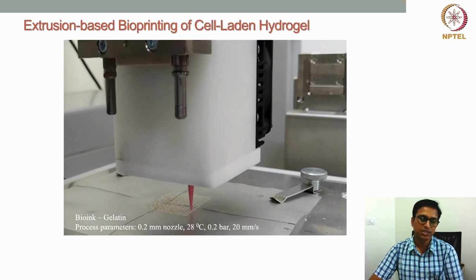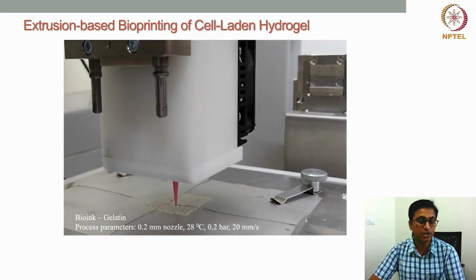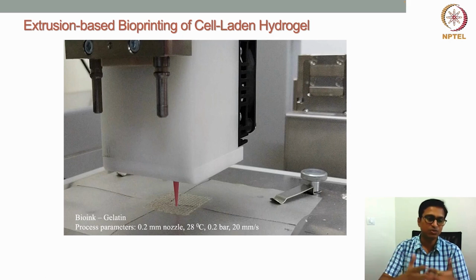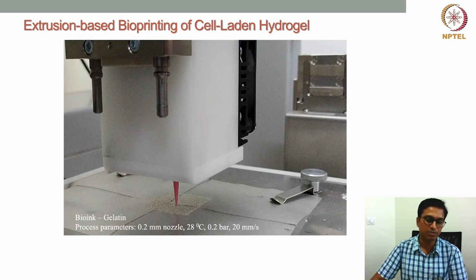But this, as I already mentioned, here the structural fidelity, the printing fidelity cannot be very good because of the nature of the hydrogel, that when you print them, they don't retain the shape of the printed filaments, but they generally deform due to the gravity. So that's what happens. But anyway, this is very important because the cells can survive this printing process. When we optimize all the printing parameters, then the cells can survive and they can very well be alive after printing within the printed structure. So if we can optimize all the printing parameters nicely, then the cells can survive this process, and cell viability can be more than 80% or more than 90% cells can be alive.